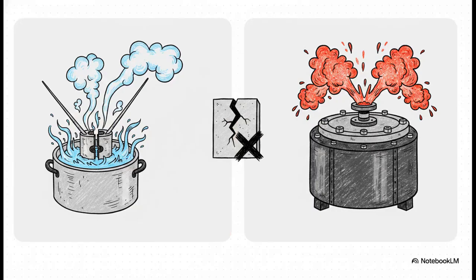Next up, we've got a test for soundness to guarantee the cement won't dangerously expand and crack once it finally sets. We use two methods for this. The Le Chatelier apparatus tests for excess lime. It uses a small 30mm mold where the indicator arms must not expand more than 10mm after boiling, all while using 78% of that P water value. The autoclave test, however, steps it up and tests for both lime and magnesia. And guys, we're talking about subjecting the cement to a violent 21 kilograms per square centimeter of steam pressure for 3 straight hours. Even under those brutal conditions, the expansion must remain strictly under 0.8%.